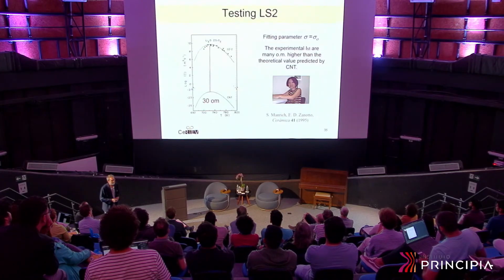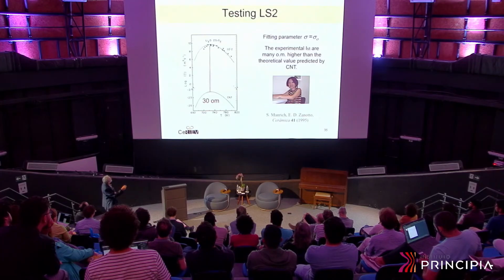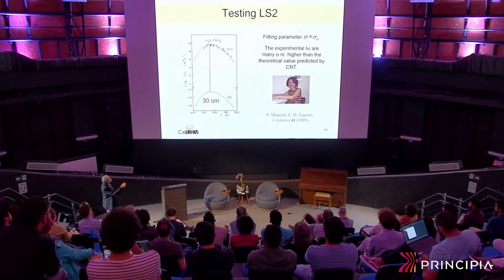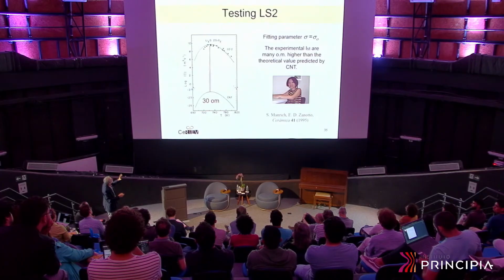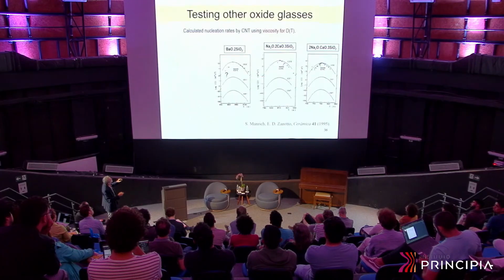Went up 30 orders of magnitude. You see the temperature dependence. This is the calculations, and the data is here. The temperature dependence is quite well described, but not the magnitudes. And there's some noise here, but forget this, it's another problem. But overall, this is what we found, and many people did this for other systems, barium disilicate, soda lime silica,